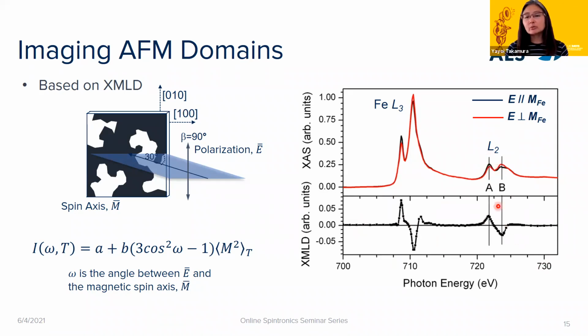So for the imaging, I'm going to take two images now. The two images are going to be at a fixed polarization, but at two different energies: one at the A peak with a positive XMLD signal, and then one at the B peak where you have a negative XMLD peak.